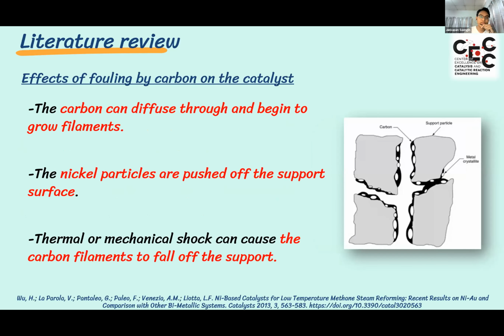For the effect of carbon on the catalyst, the carbon can diffuse through and begin to grow filaments from the backside of the nickel particles, especially at high temperature and low steam to methane ratios. The nickel particles are pushed off the support surface. Thermal or mechanical shock can cause the carbon filament to fall off the support, leading to permanent deactivation of the catalyst.